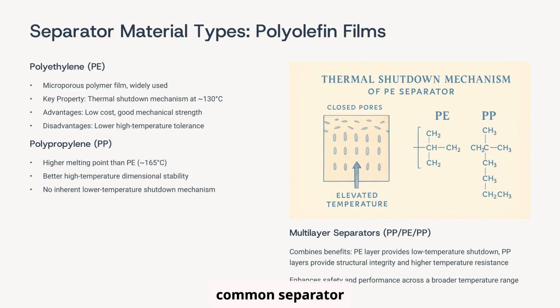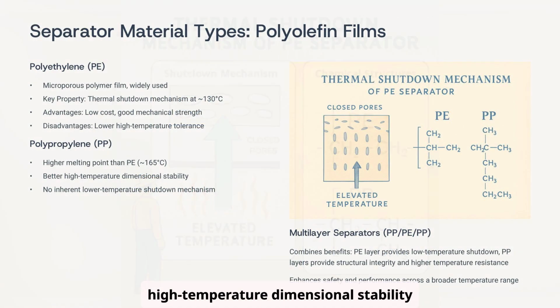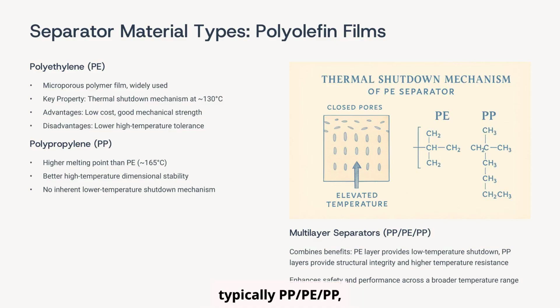Polyolefin films are common separator materials. Polyethylene, or PE, is a microporous polymer film known for its thermal shutdown mechanism around 130 degrees Celsius, offering low cost and good mechanical strength. However, it has lower high-temperature tolerance. Polypropylene, or PP, has a higher melting point around 165 degrees Celsius, providing better high-temperature dimensional stability, but lacking an inherent lower temperature shutdown. Multi-layer separators, typically PP/PE/PP, combine these benefits, with PE providing low-temperature shutdown and PP offering structural integrity and higher temperature resistance, enhancing safety across a broader range.